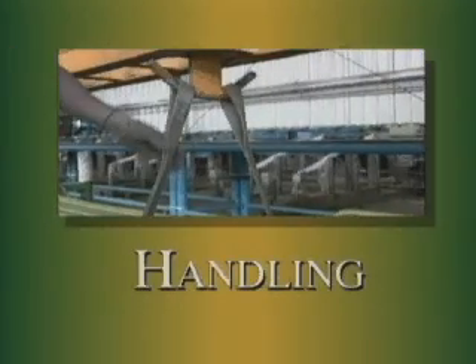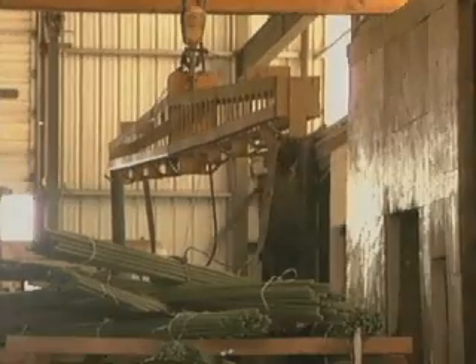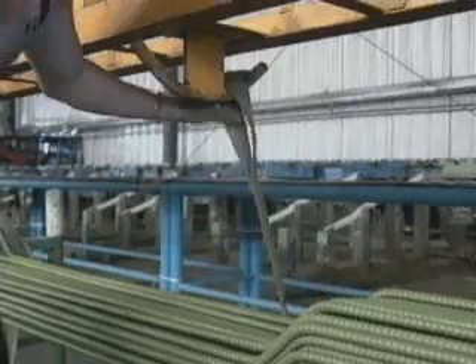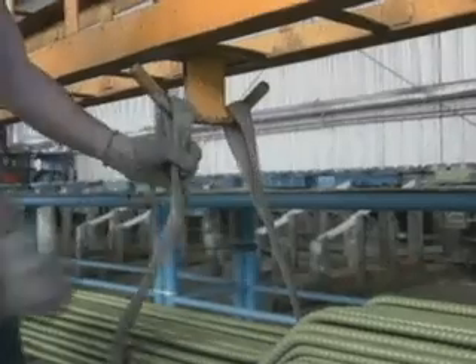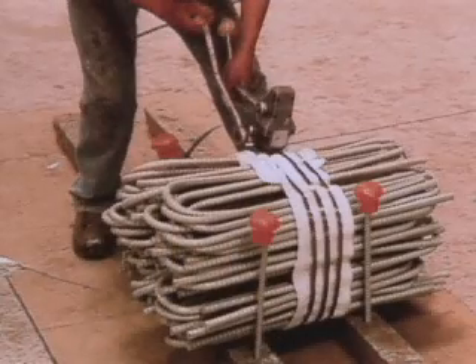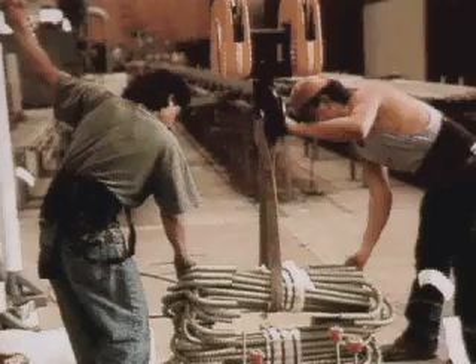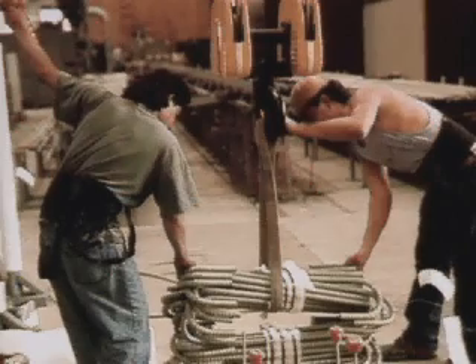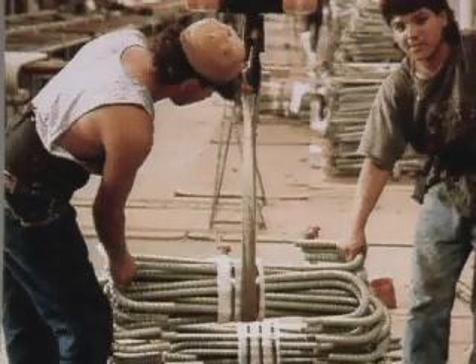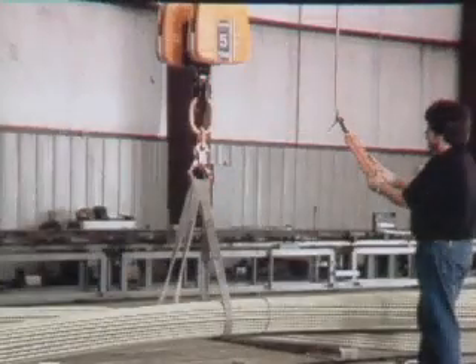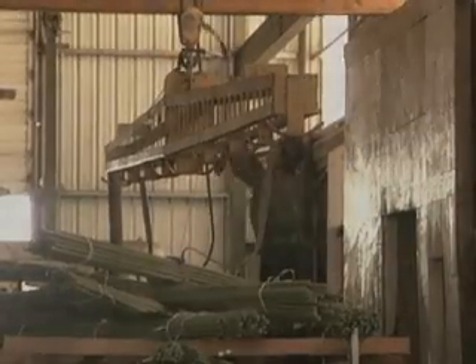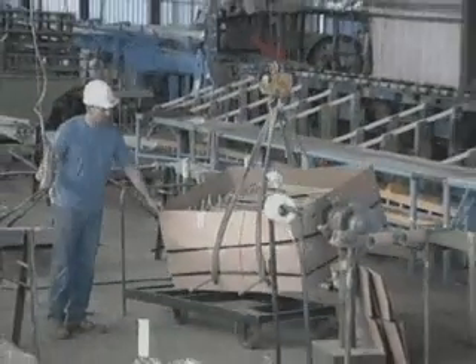When loading the epoxy-coated rebar for shipping or moving it to storage, care must be taken to avoid damage to the coating. Use nylon strapping or other non-abrasive material or padding to bundle bars to avoid damage. When you're lifting the rebar, use protective nylon or padded slings, not chains or wire rope. Make certain that you don't drag or drop bundles. When using power lifting equipment, use a spreader bar, a strong back, or multiple pickup points to minimize sag in the bundles.